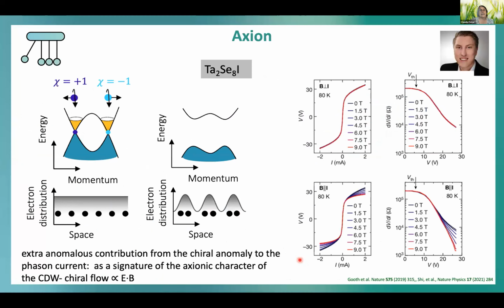So this was the proposal. We have a Weyl semimetal, which is the DFT band structure. And because of the correlation effect, we have a charge density wave, and this charge density wave is then responsible for opening up a band gap. So what we did here is we tried to slide the charge density waves. This was also the proposal.